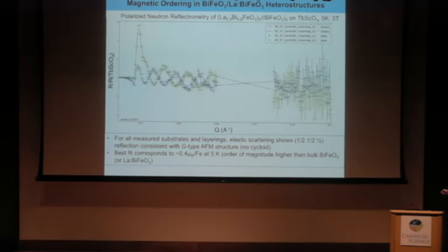So in this case, this looks really impressive because this splitting should all come from magnetization, but I should warn you that terbium scandate has a really large anisotropic paramagnetism, and we couple to that too. So a large portion of this spin asymmetry is coming from the magnetization in our substrate, but because we have depth profiling, the Q dependence and where we deviate from Q gives us the ability to tell apart the magnetization in the substrate from the magnetization in the film as we fit our model iteratively. And so this fit, so you can see my fit here to this data.